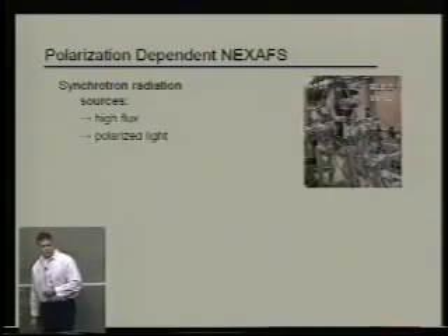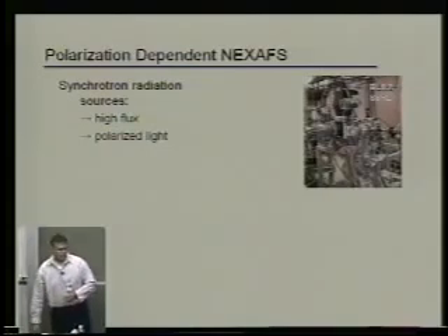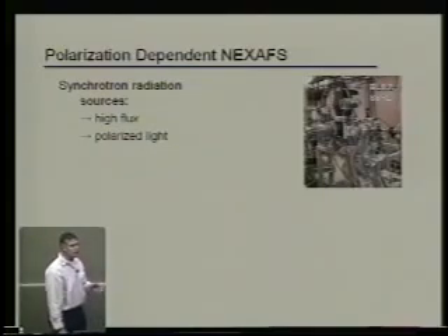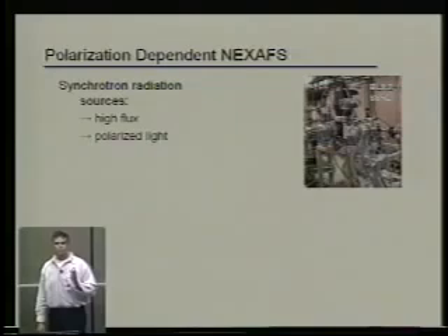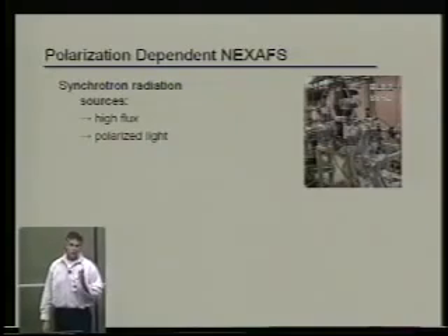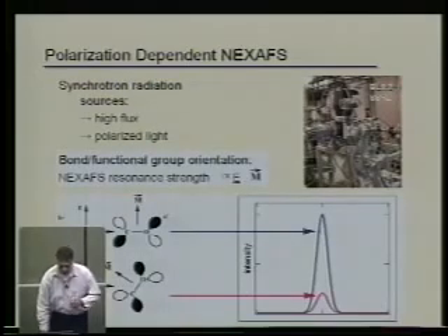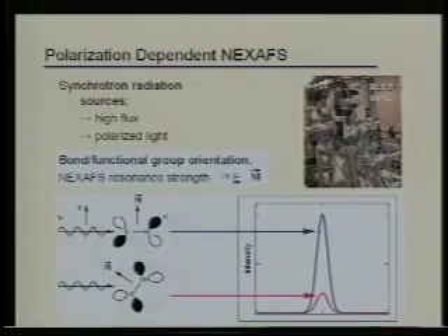So one of the other interesting things and uses for XANES NEXAFS is it's a high flux, and at synchrotrons you can get very well polarized light, linearly polarized or circularly polarized. In this case, we're interested in linearly polarized light. And what you can do is you bring your X-ray in, and it has an electric field vector. Now, I want to be a little bit careful here, because I realized this after the fact, that depending on whether you have a sigma bond in a linear molecule, or if you have pi star features in